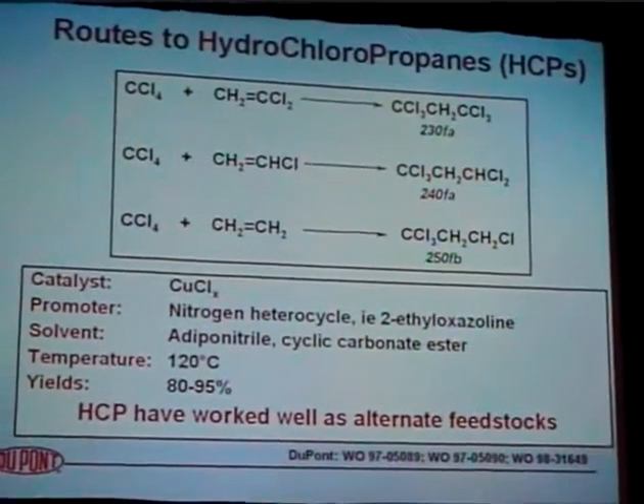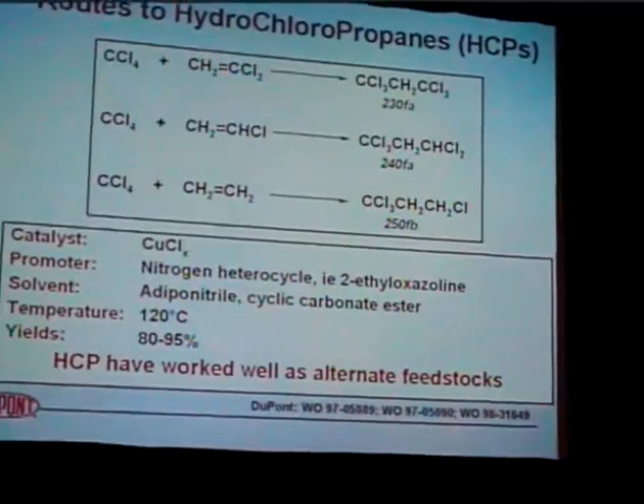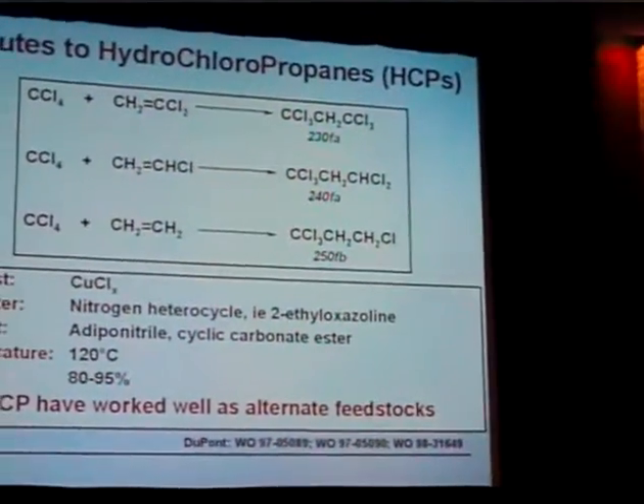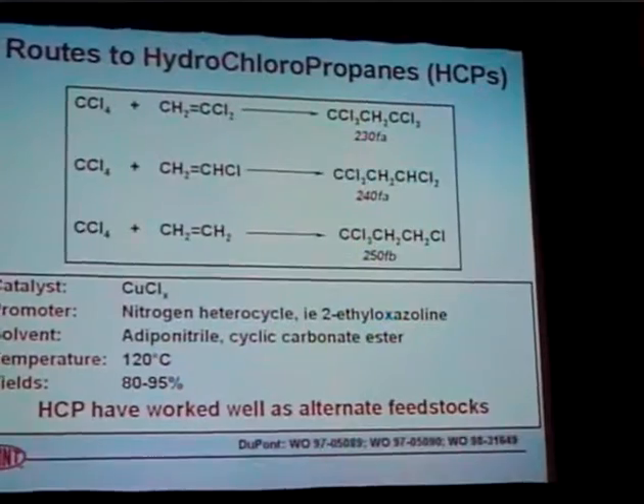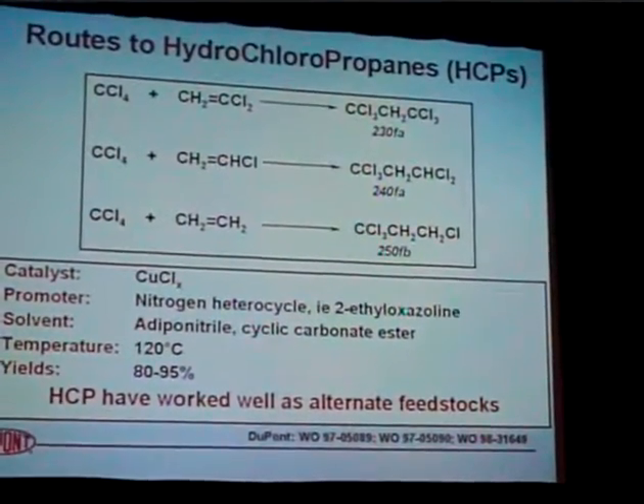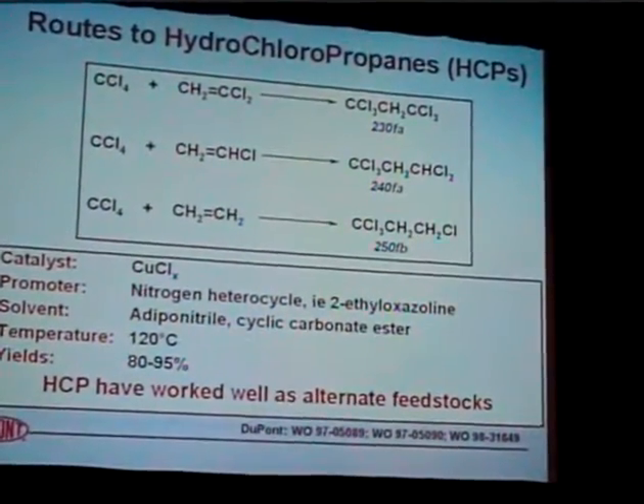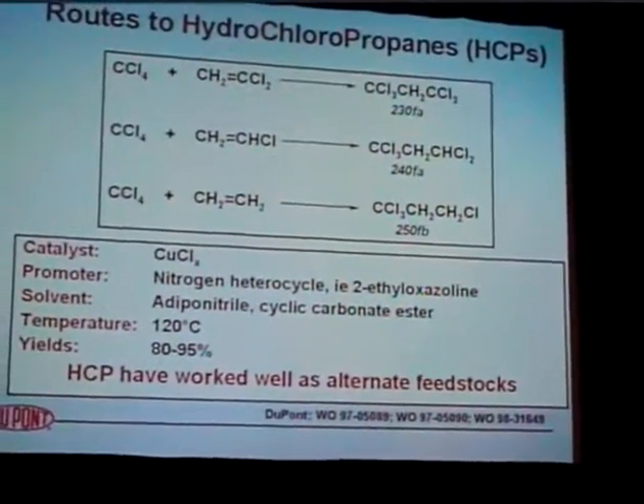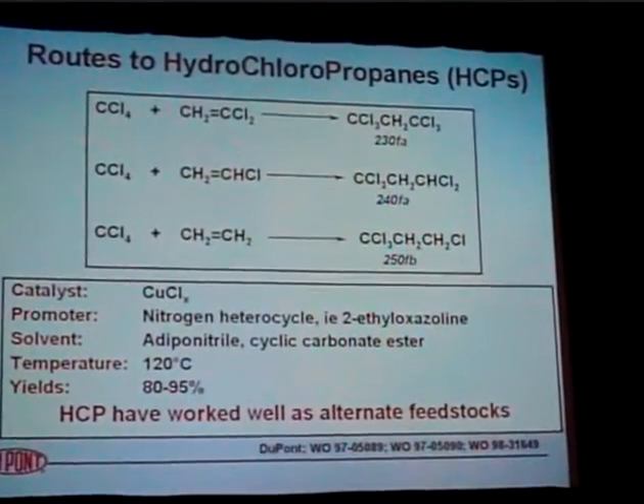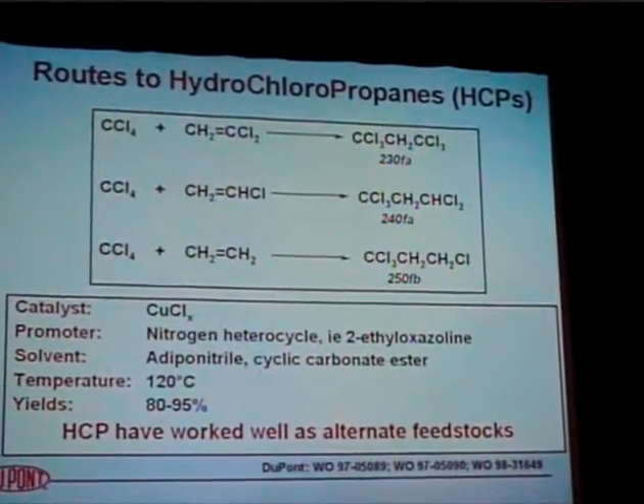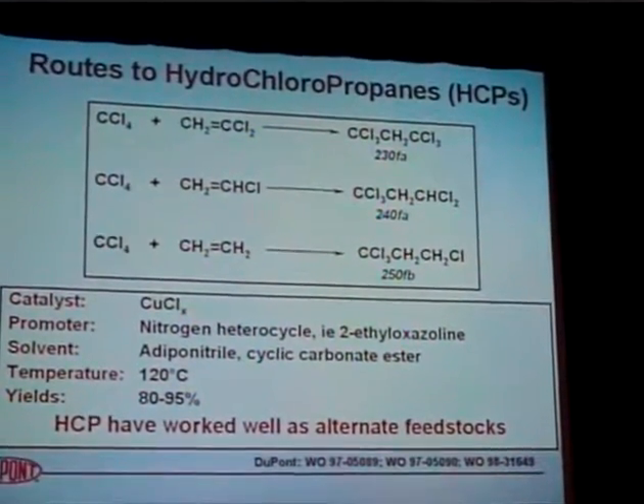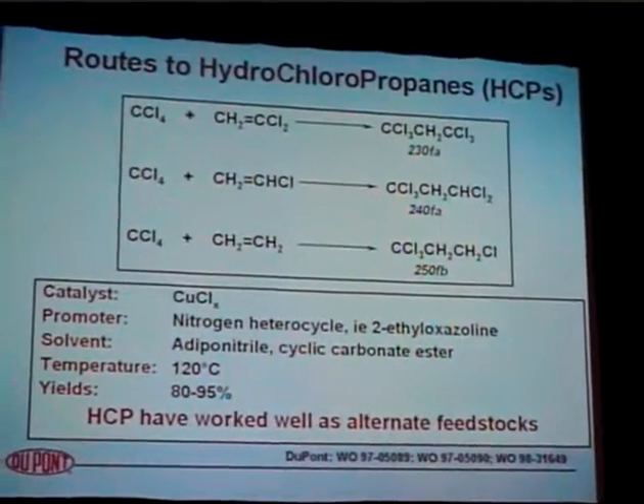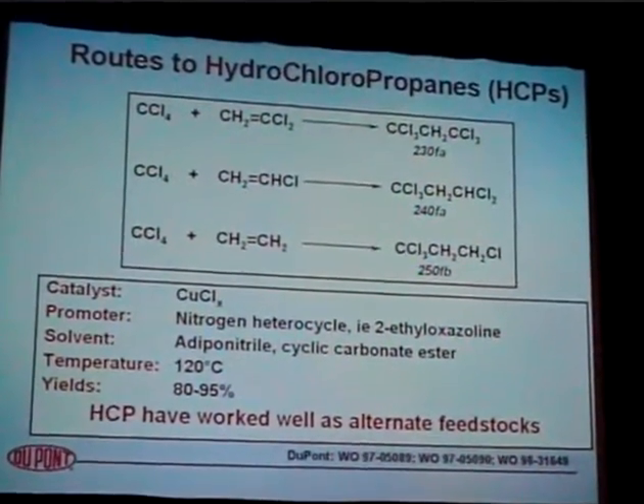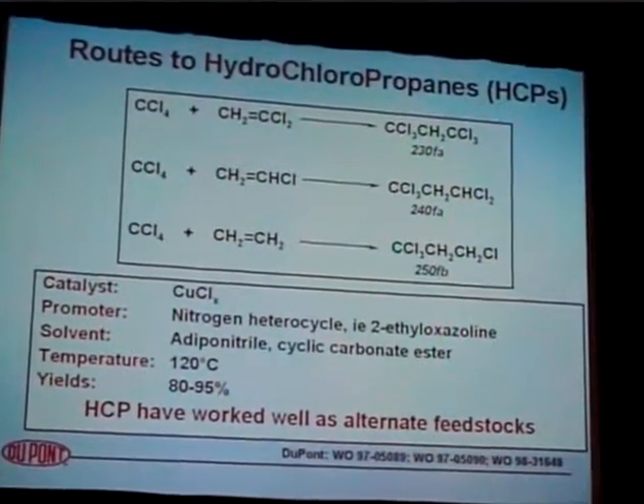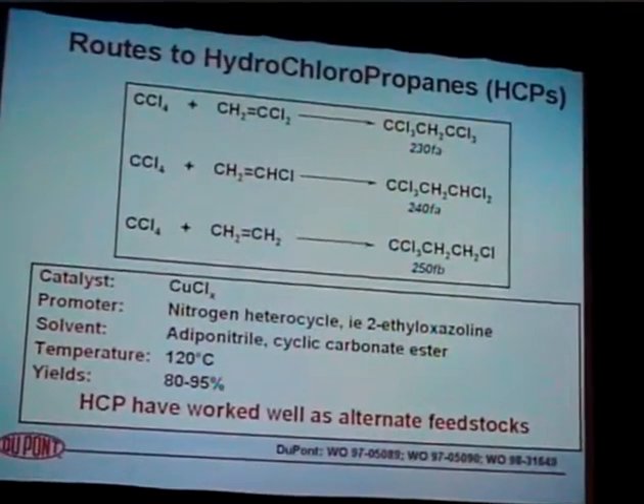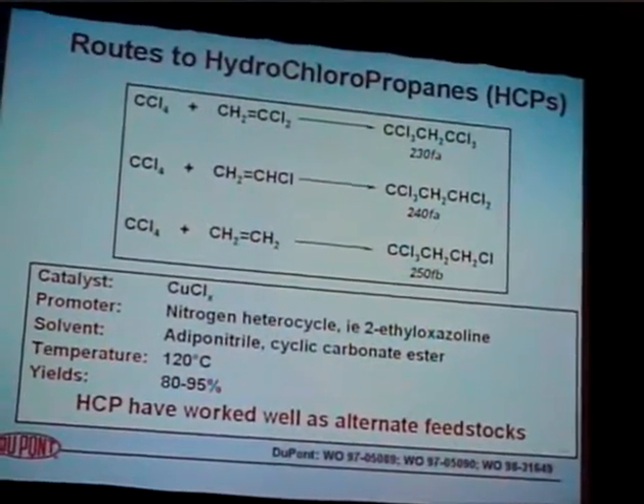The trouble is, those materials then want to add again to additional olefins, so you start to build up longer chain molecules. So the key was really stopping the reaction at the C3 rather than making C5s and C7s and C9s. That's done by using copper chloride. Very nice at stopping the reaction at the C3 step. The copper is promoted with heterocycles, such as the one shown there, the 2-ethyloxazoline. And the choice of the solvent is critical. Adiponitrile works extremely well as a solvent for this liquid phase, homogeneous, catalyzed reaction.